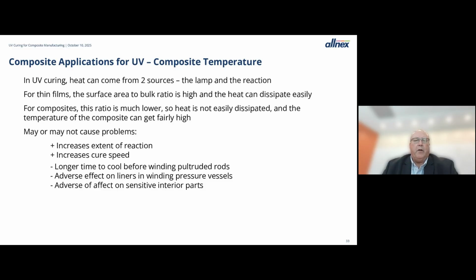From a temperature standpoint, in UV curing, you can get heat from two sources. The lamp, as we've shown before, the mercury lamps generate some heat, and the chemical reaction itself of the UV cure generates a lot of heat. So in thin films, in a typical UV coating, the surface area to bulk ratio is very high and the heat can be easily dissipated. For composites, they tend to hold the heat in because they're a lot thicker and the heat's not easily done away with. And so the temperature of the composite can get fairly high. That may or may not be an issue, but it's something to consider. Higher temperatures generally increase the extent of reaction and increase the cure speed of the reaction. So that could be a positive.